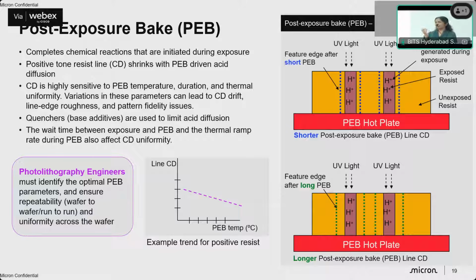So all of these parameters have to be very carefully controlled, and another factor here is the post-exposure bake. Right? You're going to expose in a certain region. Now think about when you're flashing a light, right? There's a diffraction happening, there's a chemistry change happening, yet it is so finely tuned. And I know Dr. Gandhi mentioned quenchers. That's what these photochemicals actually have, so that the deprotected acid that gets generated in a photoresist film on exposure gets directly tuned to the desired feature. However, with slight bake changes, you can adjust the profile, you can adjust the roughness of the features. It has to look like a rectangular feature at the end of the day. So very, very finely tuned chemicals.